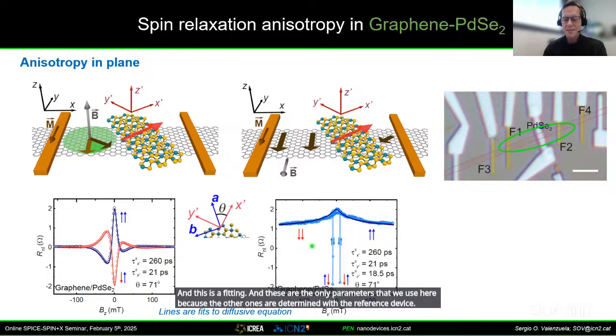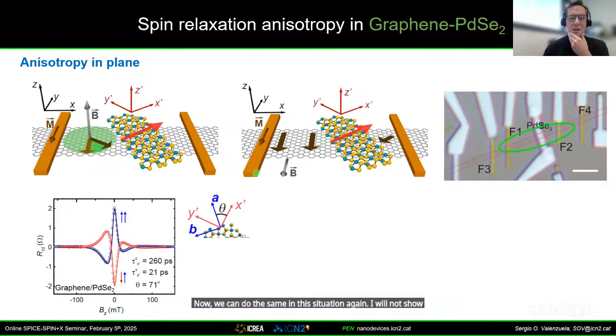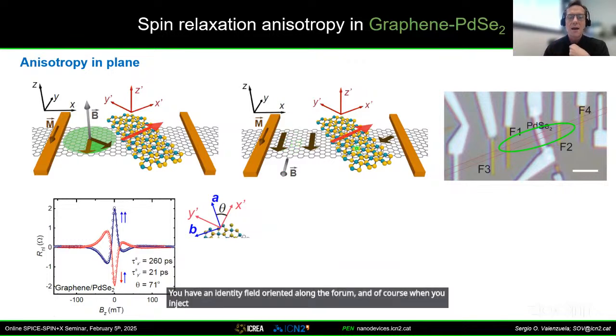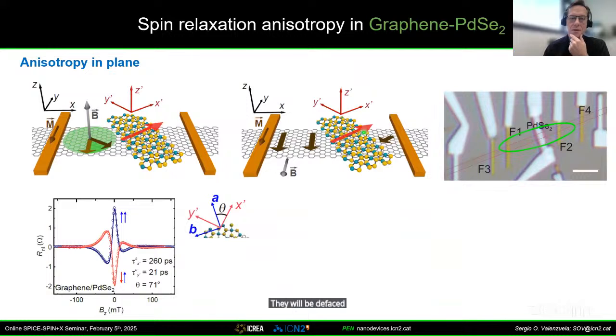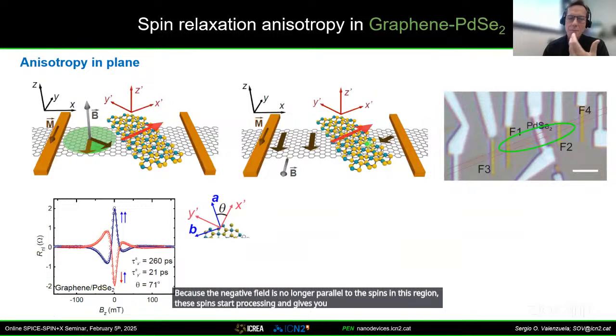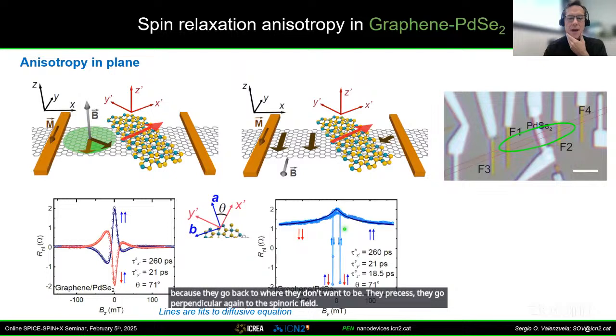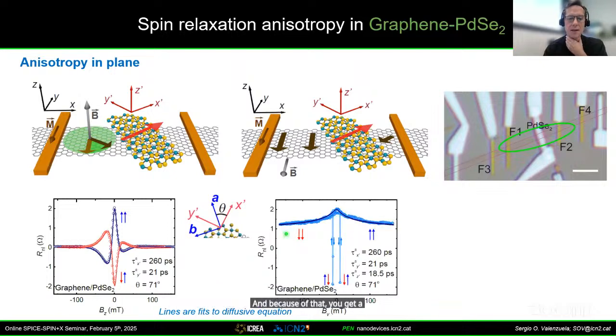Now, we can do the same in this situation again. I will not show you this to not spoil it. You have a magnetic field oriented along the ferromagnet. Of course, when you inject the spins, they will not precess. However, when the spins reach this region, they will be dephased because of the spin orbit fields that you have there. They will come more parallel to the spin orbit field in a sense. Because the magnetic field is no longer parallel to the spins in this region, these spins start precessing and give you an additional component for dephasing because they go back to where they don't want to be. They precess, they go perpendicular again to the spin orbit field. And because of that, you get a decrease in the spin signal, as you can see here.